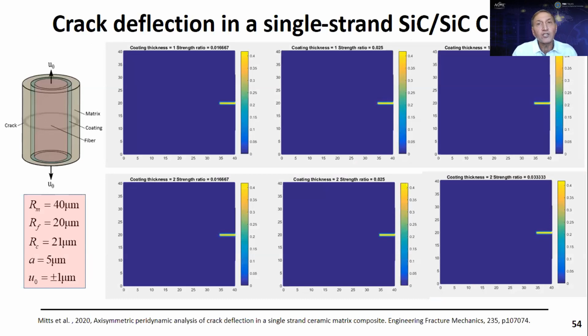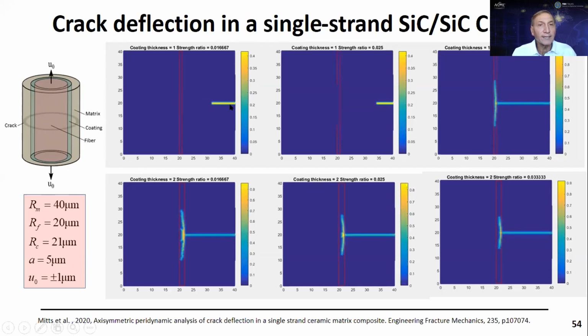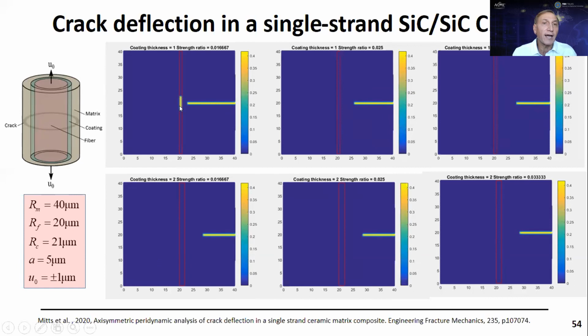Next, I'm going to show you crack deflection in a single strand ceramic matrix composite. What you see here is I have this fiber and it's surrounded by this matrix. Then we have the surface crack here. And here what happens is I have a primary crack, that's the surface crack. As it propagates, depending on the strength of the interface, the secondary crack initiates, they coalesce, and then the crack gets deflected. So the distance varies depending on the strength of the interface. And also the thickness of the interface matters.